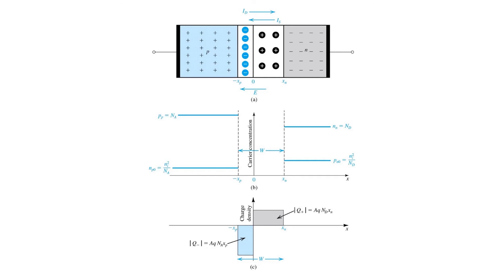So far, our cartoon drawings of the P-N junction have looked pretty symmetric, but in reality, usually they're quite asymmetric. Specifically, one side is usually much more heavily doped than the other side. In fact, the difference in carrier concentrations can be several orders of magnitude, so much more than is being illustrated here even. When that's the case, only a very thin depletion region appears in the more heavily doped side. A much wider depletion region appears in the more lightly doped side because ultimately, there's got to be a charge balance in steady state with electrons that moved from right to left recombining with holes on the left side of the P-N junction and vice versa. Such junctions are therefore often called one-sided junctions because the vast majority of the depletion region appears on one side of the actual junction.